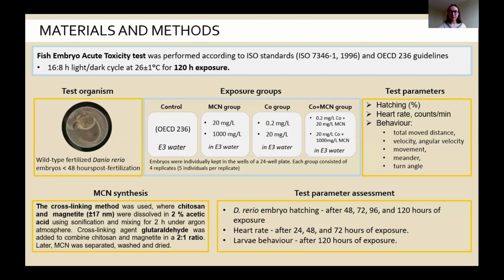And the parameters that we tested were hatching, heart rate, and behavior, including total move distance, velocity, movement, meander, and turn angle. The MCN nanoparticles were synthesized using the cross-linking method, where the agent glutaraldehyde was used to combine chitosan with magnetite in a 2:1 ratio.